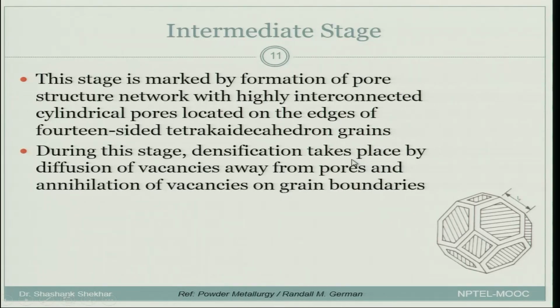During this stage densification takes place by diffusion of vacancies away from pores. So, the vacancies move away from pores and get annihilated at the grain boundaries. So, this is what describes the intermediate stage, and let me quickly write down the equation which describes this.